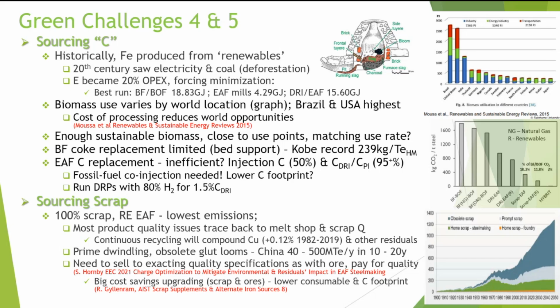But most of the quality issues with the steel trace back to the melt shop, and that's partly because of the lack of specific quality to which the scrap is sold. And as we know, prime is dwindling. Obsolete glut looms because China is predicted to put 40 to 500 million tons a year of scrap into the market within the next 10 to 20 years. And the continuous recycling is going to increase the issue that we have with copper and trace elements in the scrap as we move forward. So it's becoming a big issue.